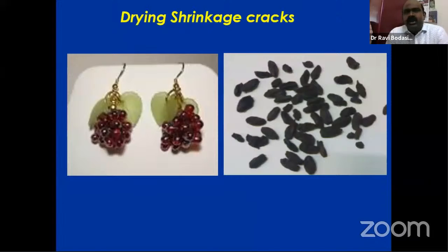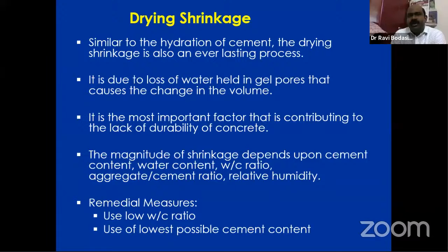So next, coming to dry shrinkage cracks. By this picture we can see grapes in a fresh state, and after they lose their water. How the volume of the grapes and the space between the grapes change clearly denotes the same phenomenon. Dry shrinkage: after losing water, the volume of the concrete reduces and it tends to crack. That cracking is called dry shrinkage. Similar to the hydration of cement, it is an everlasting process. Dry shrinkage is an everlasting process. It is due to the loss of water in the gel pores and change in the volume.